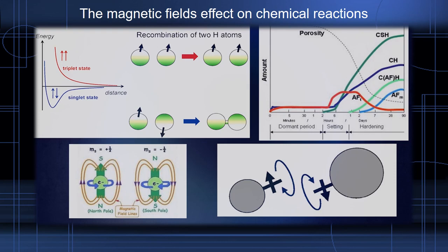We solved this problem by introducing a finely dispersed ferromagnetic magnetized substance into the composition of Portland slag cement. To reduce costs, it is proposed to use dusty waste from the metallurgical industry as such a substance. In our previous work, it was shown that the magnetic fields created by the dust additive can have a positive effect on the activity of cements. At the same time, it was revealed that the strength characteristics of Portland slag cement are affected by both the magnetization of the particles and the disperse composition.